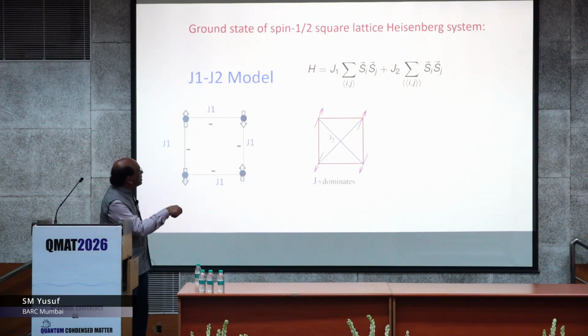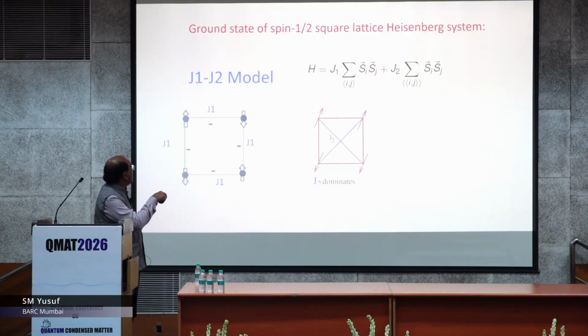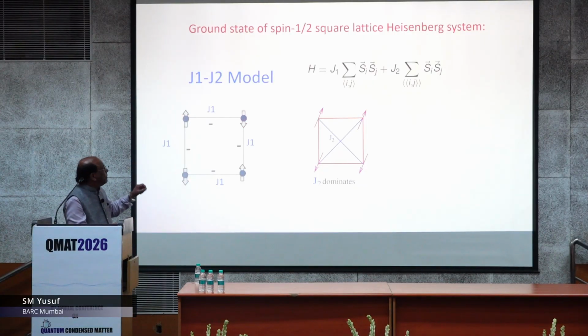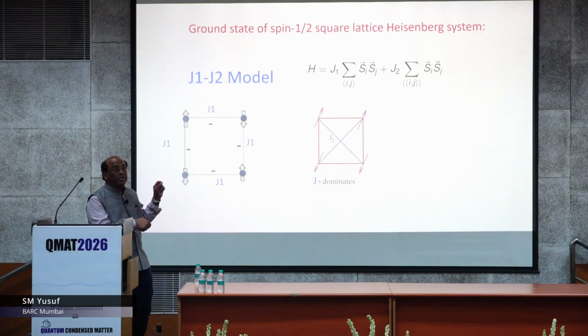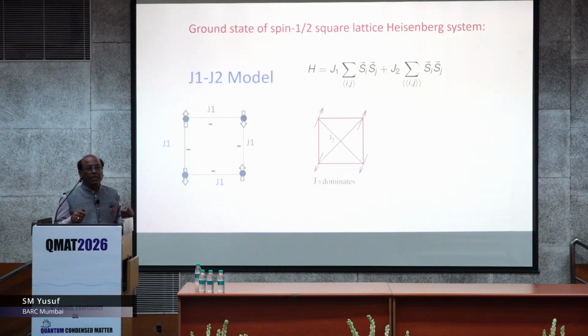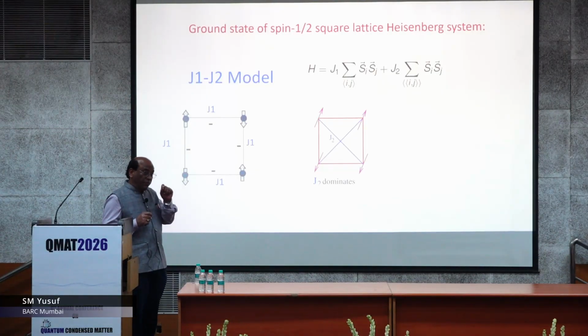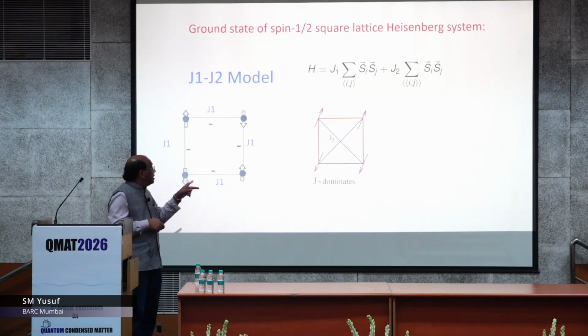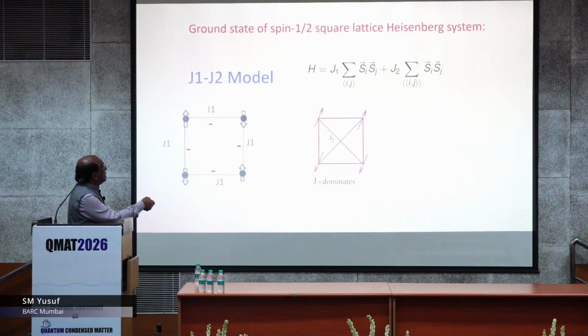Now once you also have the diagonal exchange interaction, that is the next nearest neighbor exchange interaction, this is the nearest neighbor, and that is also, let us say, negative, I mean antiferromagnetic. Because these two guys are already parallel, and if it is antiferromagnetic, this demands these two should be antiparallel. So that means this spin is getting subjected to both positive and negative exchange interaction. So this is the true example of the competing exchange interaction, both positive and negative, unlike the triangular one, where the frustrated spin is not subjected to both positive and negative exchange interaction with equal strength. So this is the clarity I wanted to bring, and the Hamiltonian goes like this, with both the nearest neighbor and the next neighbor exchange interactions.